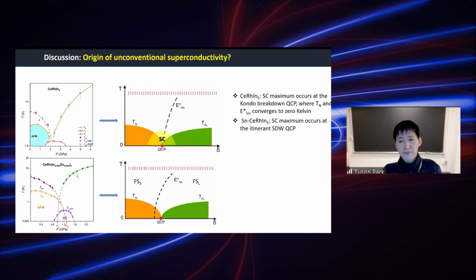So it clearly suggests that magnetic fluctuations tied to the AFM QCP mediate the formation of Cooper pairs. Okay, so to summarize the talk, we successfully moved the AFM QCP from 2.35 to 1.35 GPa, and showed that superconductivity moves together with it. And then we discovered the new temperature scale named T star L, signifying the transformation from a small to large Fermi surface phase, both in cerium rhodium indium 5 and the tin doped compound. And in the tin doped compound, we showed that the delocalization critical point actually ends deep in the AFM phase.